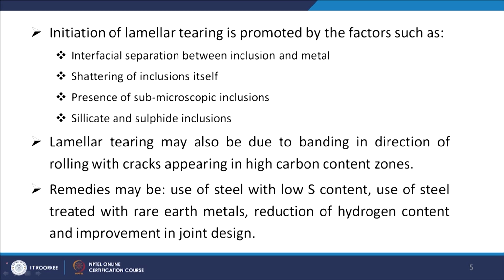We have seen that you have sulfide or silicate inclusions and oxide inclusions. So, that separation which takes place between these inclusions and the metal is one of the reasons.